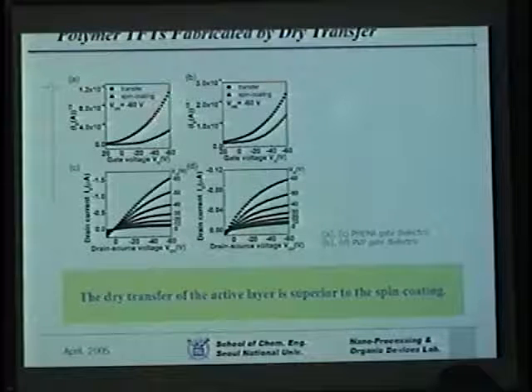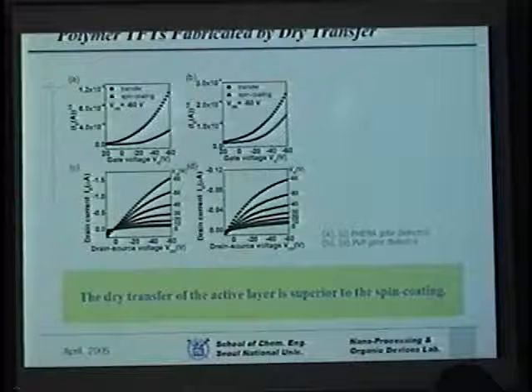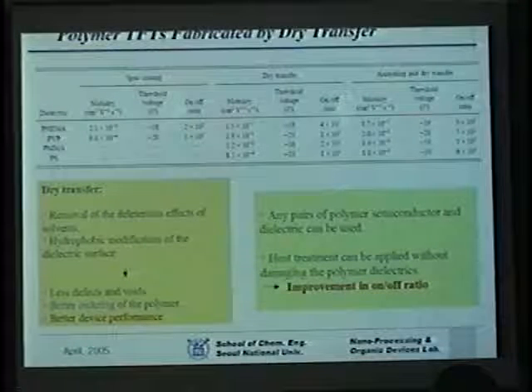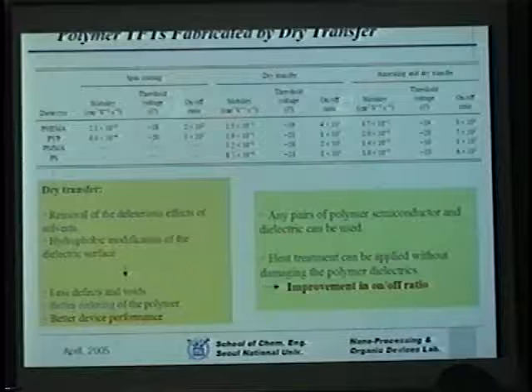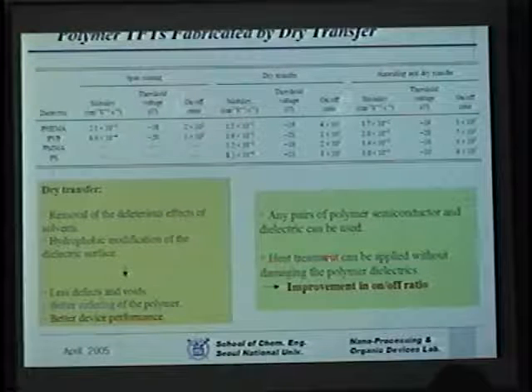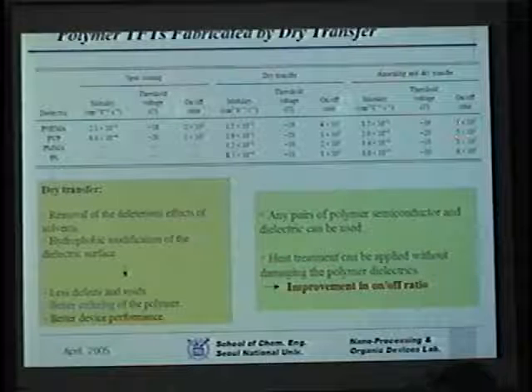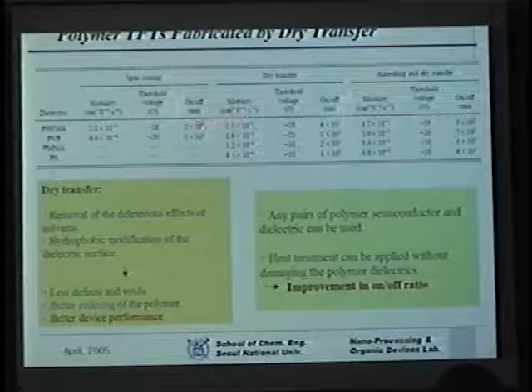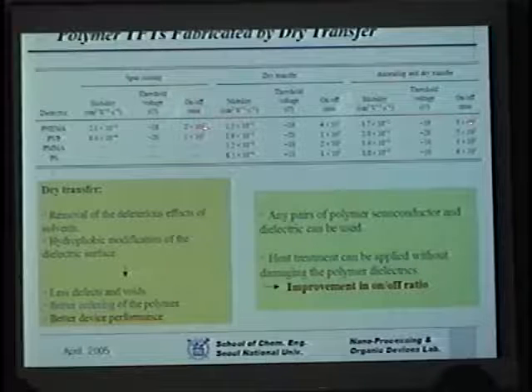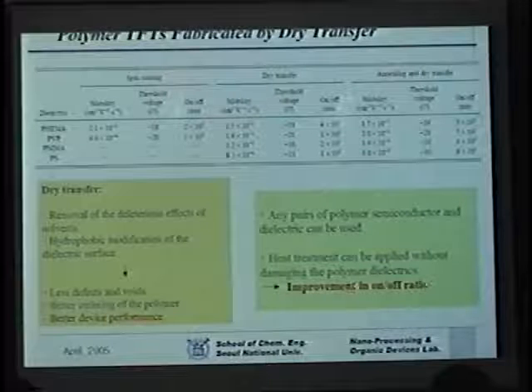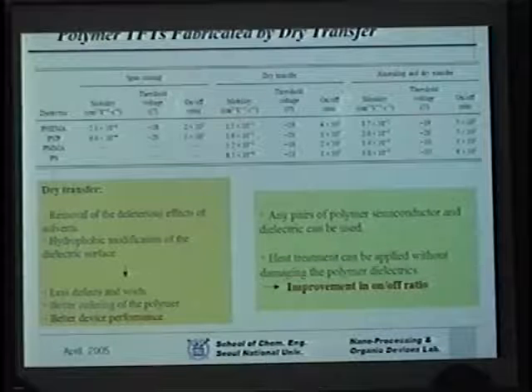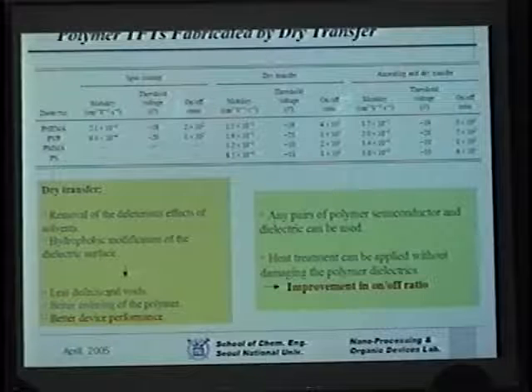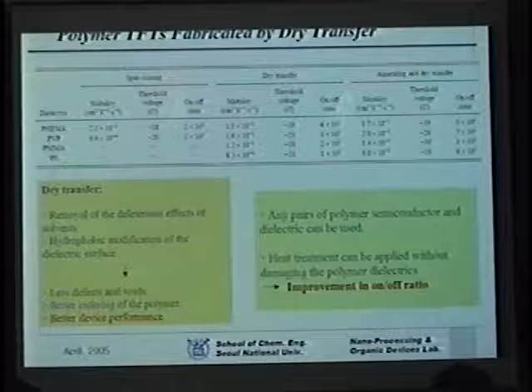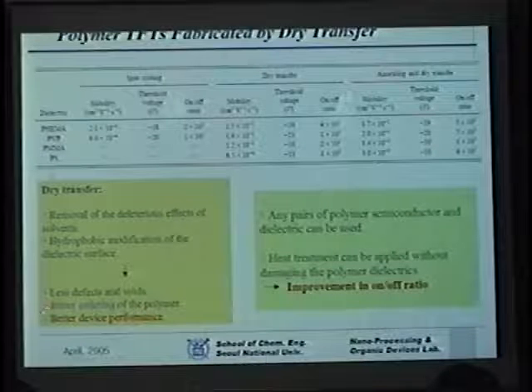you see a huge difference in the device performance. The same is true with the PVP gate dielectric. As I indicated, with the dry transfer method, you can do heat treatment, which results in improvement in the on-off ratio. That is, when you do spin coating, the on-off ratio is about 100, about 1,000. So you get some improvement in on-off ratio by heat treatment prior to the transfer. And because you do not use solvents, you do not generate defects and voids. You can allow better ordering if given sufficient time, which in turn leads to better device performance.